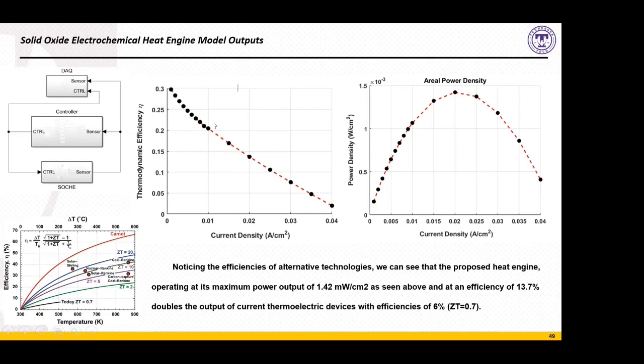This is not the Carnot efficiency. This is the thermodynamic efficiency. Even here at the maximum power point, if we ramp up the current density, we can get a power density of about 1.42 milliwatts per centimeter squared. Even at this maximum power point, we have an efficiency of about 13.7%, which doubles the efficiency of current solid-state thermoelectric devices that oftentimes have efficiencies on the order of 3 to 6%. Now, further analysis needs to be done in the packaging of this system and how the power densities would compare to, say, the power densities of solid-state thermoelectrics. But at least the system as envisioned here seems promising.